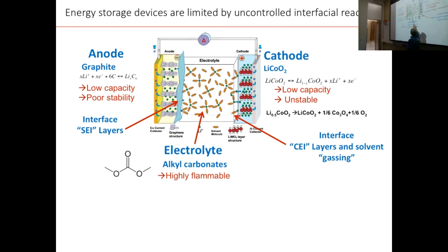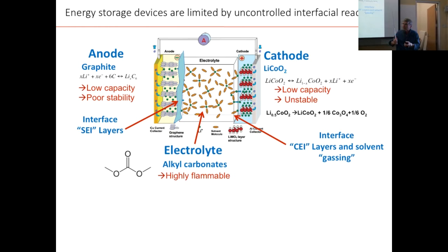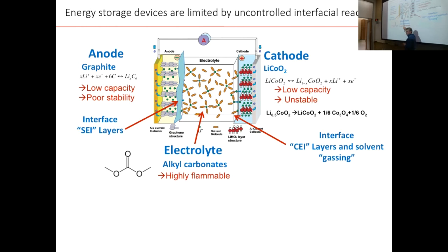If these solvent molecules get between the sheets of graphite, they push the layers of graphite apart. It's called exfoliation. The little layers begin to come apart, and the electrode basically crumbles, right? It just falls apart mechanically because of the mechanical stresses. So in fact, the reason when you get a lithium-ion battery or whatever it is, your recent device, they always tell you to charge it up the first time before you use it, right? The reason that you are doing that is you are making sure before you use the battery that you have formed a good SEI layer.